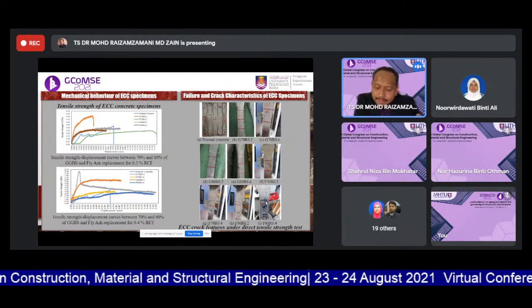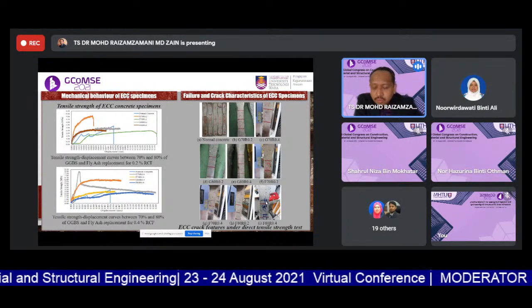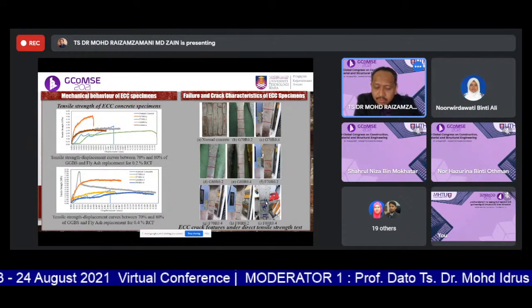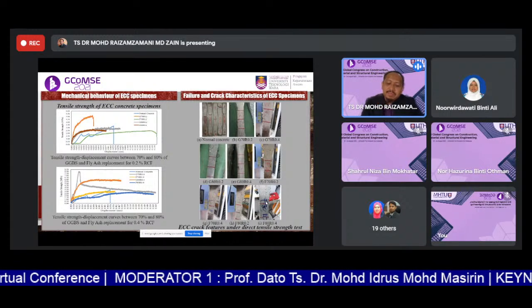And what we can see here is that cracking during the tensile strength test was mostly observed in the middle of the dog bone specimen. However, we can also observe the crack at 1/3 from the middle sections of the specimen.